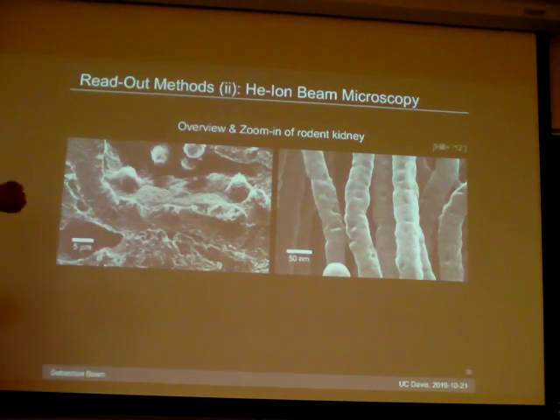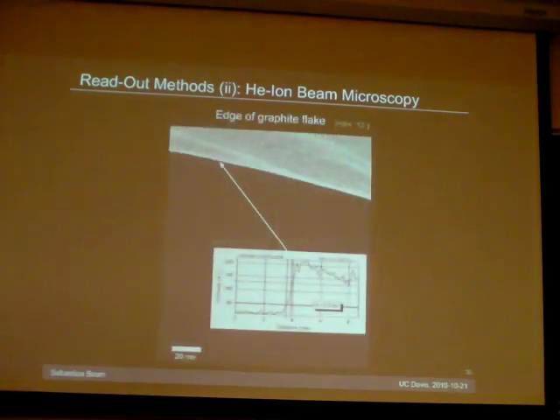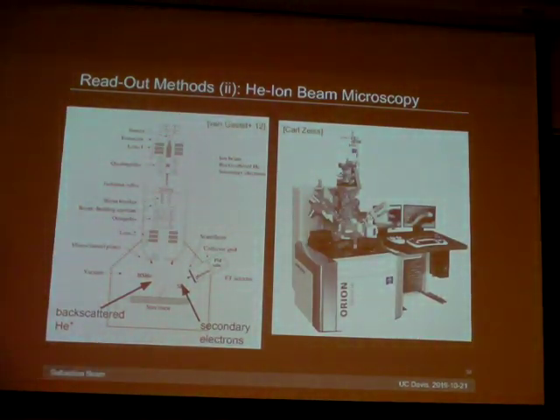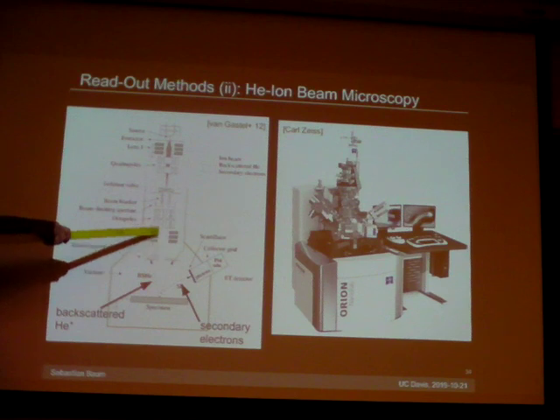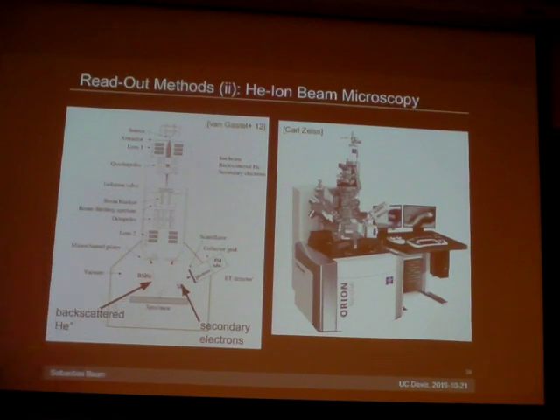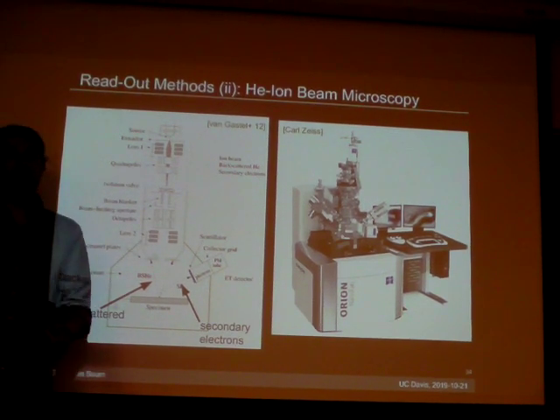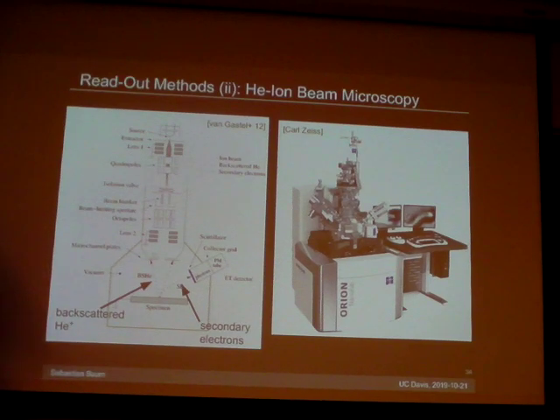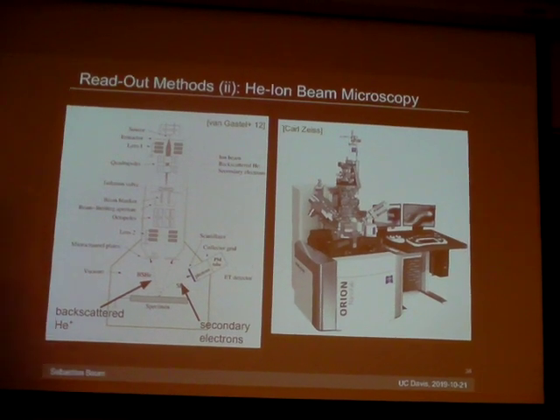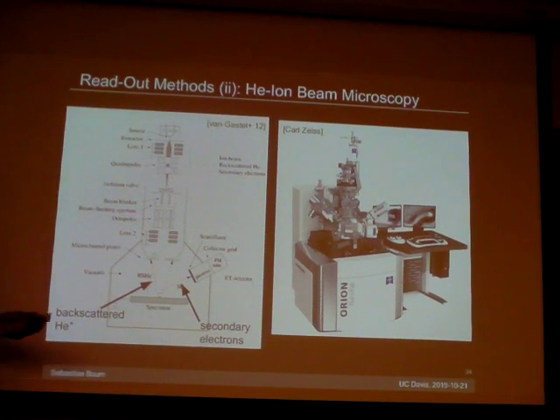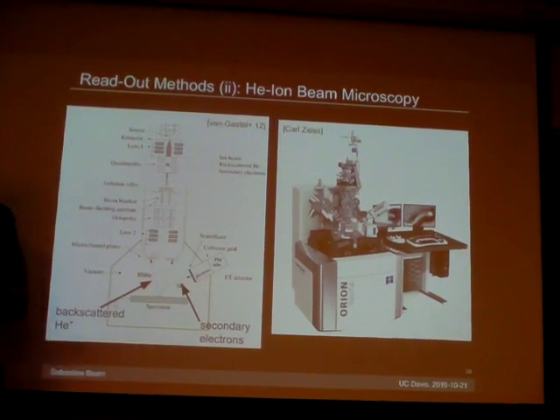Again, you see I don't show you tracks, right? So this hasn't been demonstrated for tracks, although we don't see any reason why, and people we talk to don't see any reason why this couldn't be done for tracks. So there is one additional complication, right? What you're doing is you shoot a low energy ion beam at your target and you look for backscattered stuff. So you're not going to be able to read out a bulk sample in this way, but you're only going to be able to see some surface of it. And it can read out something like 100 nanometers deep or so.